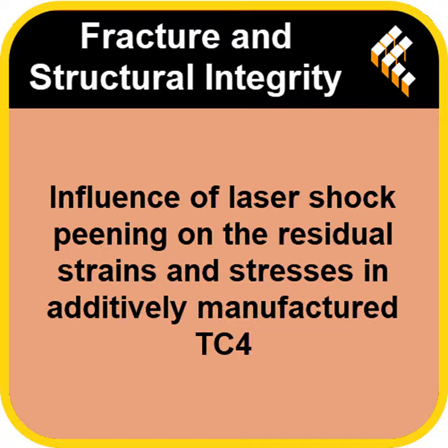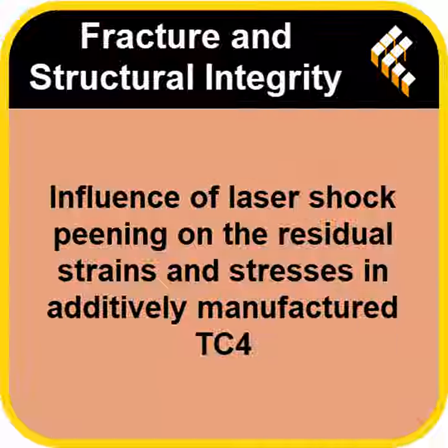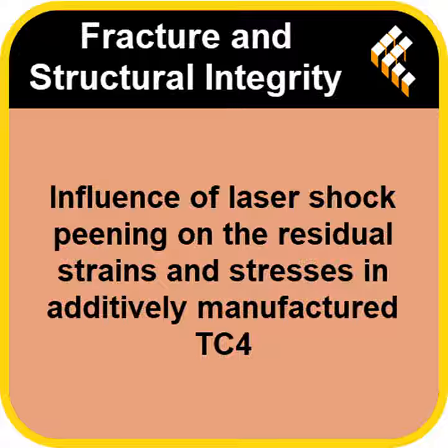Totally revolutionary. But there's a catch, a kind of built-in flaw, right? That's the core issue. When you print metal layer by tiny layer, you get these cycles of intense heating and cooling, really rapid. And those extreme temperature changes, those thermal gradients, they bake in a problem: residual stresses. And they're the bad kind, tensile stresses. Tensile, so pulling forces. Exactly. Forces that can compromise the part's strength, its integrity, maybe even shorten its lifespan before it's ever used. So that's the conflict we're digging into.